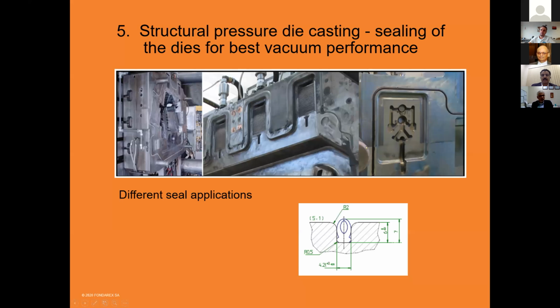So we can see here, I have made 2 or 3 different examples. Unfortunately, I'm not able to show all of them. But if a seal goes all around the cavity, far away from where the parting line is, it can make sense why the metal doesn't reach the seal. Even better is to get a second level. If we have the level, or like here also where the vacuum valve is, even if it flashes sometimes, the metal is not getting directly on the seal. So therefore also the molds are getting bigger, and you have to have the space to put the seal into the mold.